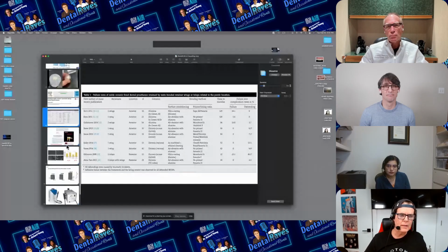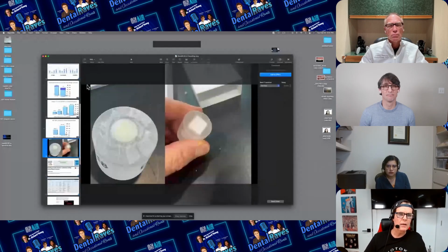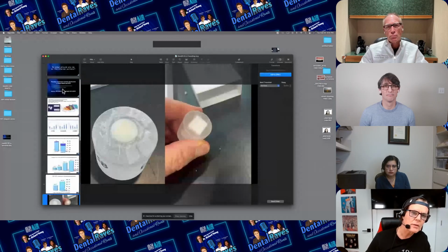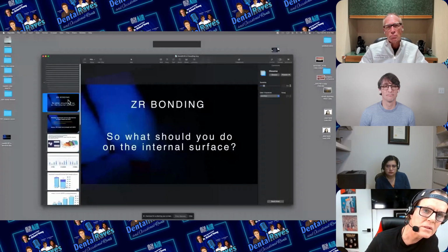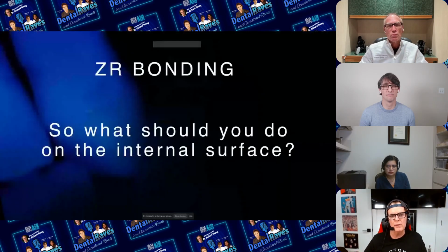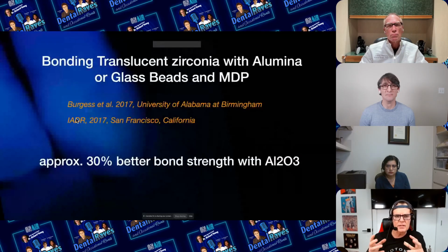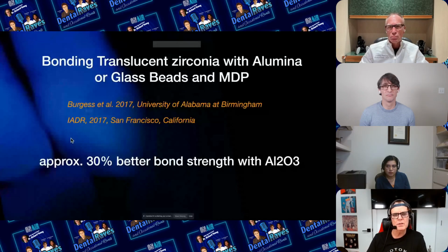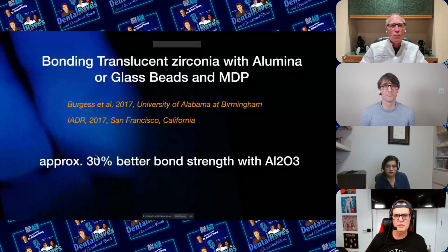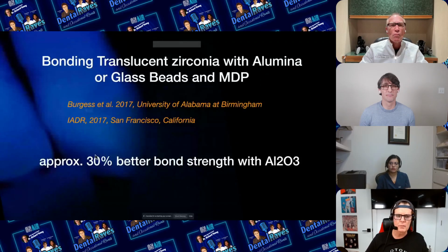So what I did was look at different surfaces. We've done some stuff on this over the years. So let's just go ahead and do this right now. What should we do on the internal surface? Now, John Burgess, and I was part of this et al., looked at the distinction between how much of the bond strength would come from just the chemistry of the MDP primer and how much would come from the sandblasting. And he found that roughly 30% better bond strength came from aluminum oxide. But this was on machined surfaces. So machined surfaces already have a little bit of roughness.